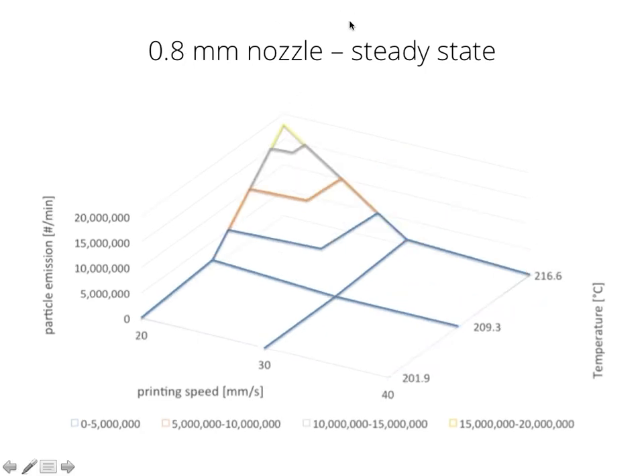You can see that the slowest printing speed has this extreme curve up. As you increase the temperature, the particle emissions increase quite drastically, from a few million up to around 17 million, while the 30 and the 40 are actually low particle emitters, or are not acting so extreme with temperature.